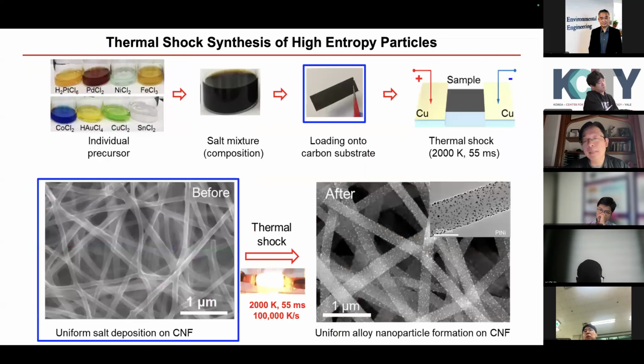So this is the idea, how to do it, right? So basically, we have the salt. You can also have the elemental powder. You mix them, and then you just heat it up, okay, to a very high temperature, and you quench it down right away. So the typical process is less than 1 second. So that also means you can continuously manufacture it by a flowing method, by dropping the particles through the heater, right? So you can see here left and right, it's only 55 milliseconds at 2000 degrees C, you can make these beautiful nanoparticles. So this is the process.